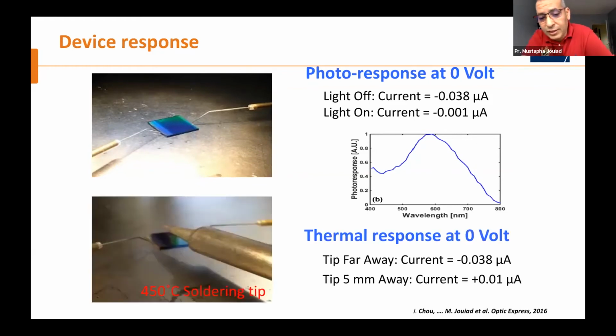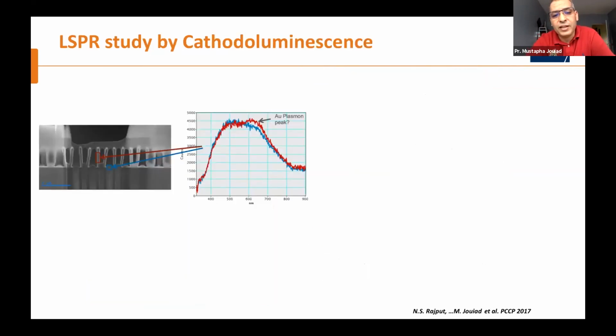Similarly, this device has double interest because even with heat, it will render some current. So we just put a soldering tip next to the device and we measure some current with the low voltage on the edges in the connected of this device. So with sunlight heating and sunlight also the absorption, both of them will create some hot electron that we are looking for to actually inject in the conductive wire of titanium. So now we will check if this hot electron really exists.